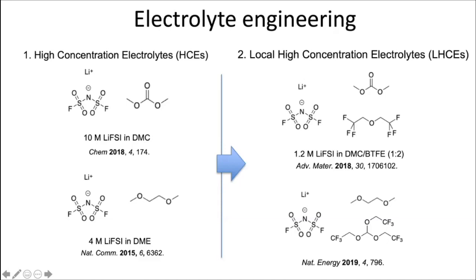The ion conductivity can suffer in this case. So the improved method reported by the PNNL is a localized high concentration electrolyte. Basically, a solvent that doesn't solvate the lithium salt is added. And the lithium salt is hypothesized to still be highly concentrated in the region and solvated by the carbonate or ether. But then these highly concentrated solvated regions are dispersed in the non-solvating solvent, slowing down the reaction and increasing the stability towards lithium metal.